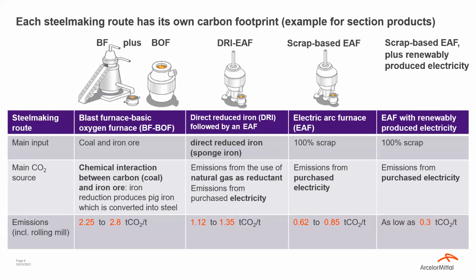Then if we go to EAF, using 100% scrap, which is what we do here in Luxembourg to produce our sections, we once more divide the order of magnitude by 2, roughly 700 kilos of CO2 equivalent per ton of steel. And if on top of that, we are still using EAF but with renewable electricity, we can once more divide the impact roughly by 2. This is to give you some orders of magnitude, to understand that if we are working with one production route or the other, of course, first of all, we are talking about different carbon impacts, but also about different decarbonization strategies and different timelines. Depending on the production route, some low-carbon solutions already exist or are ongoing, and it's important to have a good understanding of all of that. Next slide, please.